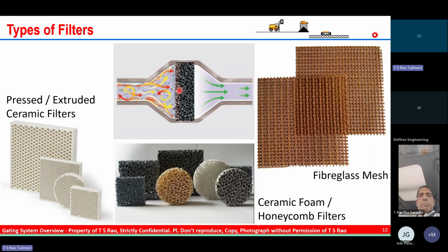The next one is fiberglass mesh. Mostly the fiberglass mesh is used when we tap liquid metal from the furnace to the ladle. Then within the mold or above the mold, we will use either pressed filters or foam filters. And you can see the various shapes of the filter depend on your pouring cup and the filter print. You can use various sizes.